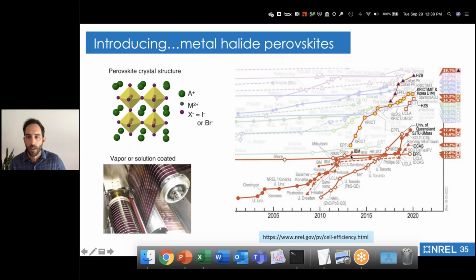And then sort of in, let's say 2013, I would say, perovskite stepped into the playing field. And what happens here is this is the line with yellow dots and red rings around them. And so if you look at 2013 and look up into 2020, the increase is dramatic. It started high and it continues to increase. Now we're already up to about 25% power conversion efficiency.